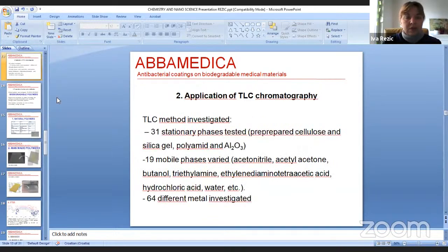So, as you will see, during the application and development of this chromatography procedure, we investigated 31 different stationary phases, which were combined with prepared cellulose, silica gel, polyamide, and alumina oxides. We created 19 mobile phases and varied different organic solvents like acetonitrile, acetylacetone, butanol, triethylamine, ethylenediaminetetraacetic acid, hydrochloric acid, water, and others. And as metal ions, we combined the experiments with 64 different metal ions.